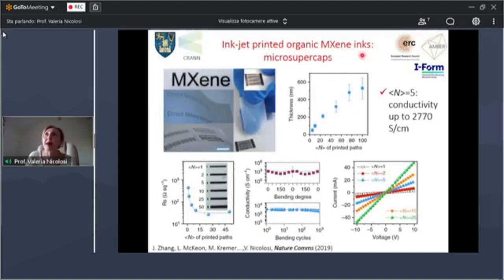Here we are using MXene inks in organic solvents. In this case, we do inkjet printing, and you can use interdigitated geometries. You can print in series, you can print in parallel. You can really open up your imagination and use the advantage of the freedom. We saw that after only 5 passes of printing, you can have a massive conductivity of about 3000 Siemens per centimeter. And the conductivity did not drop even upon bending. So these devices were fully bendable.